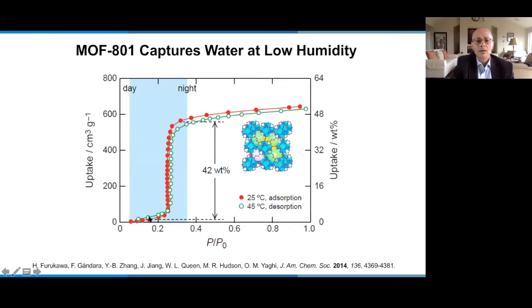So we were looking at water interaction with the framework as well, and discovered that in this MOF, this is called MOF-801, which is a zirconium MOF linked by a simple organic linker, it takes up water, let's say at room temperature, in the red here, and you see that it takes it up at very low humidity. This humidity is around 20% relative humidity, and it gives up the water in green at relatively low temperature, 45 degrees C. 42% of the structure by weight can be filled with water.